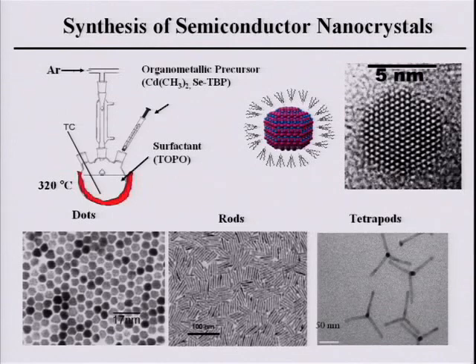Another type of nanomaterial I have been working on for the last 3 years, while I was still a postdoc at Berkeley, is semiconductor nanocrystals. This tiny crystal has a size between about 1 to 10 nanometers. It's based on purely chemical synthesis in a very hot organic surfactant. You can inject molecular precursor into this flask, and these precursors decompose to nucleate and grow into these so-called zero-dimensional nanostructures. Depending on what kind of molecules and surfactant you have in solution, you can produce spherical quantum dots, nanorods, one-dimensional structures, or even branched structures. In this case, it has 4 arms, and we call it a tetrapod.